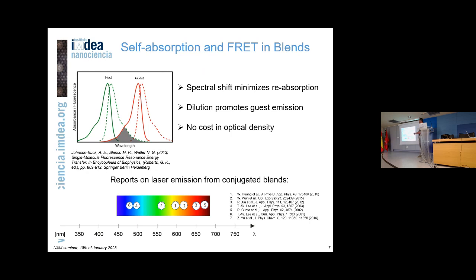For instance, if you have one molecule that emits in the green, you get very large self-absorption, but you can shift the emission of the molecule away from the absorption by doping the film with a second molecule, whose absorption is located precisely overlapping with the emission of the first one. This way you can efficiently shift the emission away from the absorption, and on top of that, you can also promote emission because you are diluting the second molecule. This is a strategy that has been followed by many groups, and we have also worked quite a lot with molecules coupled by Förster resonance energy transfer for lasing.